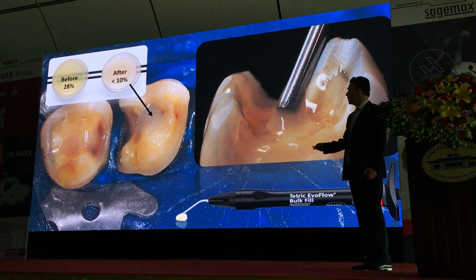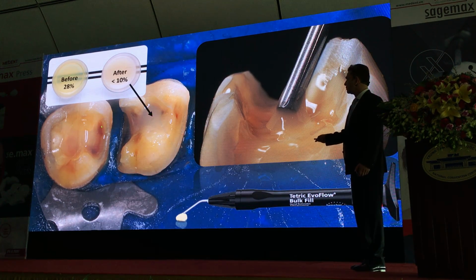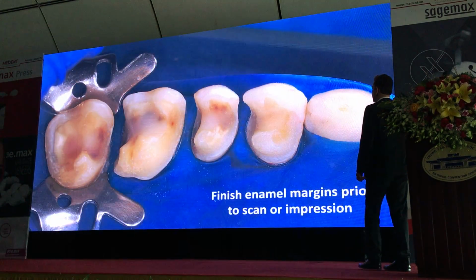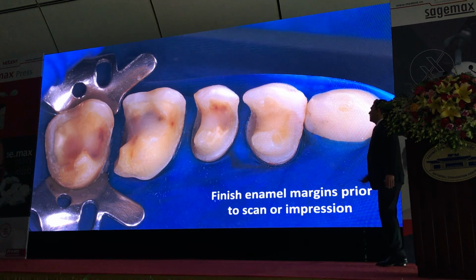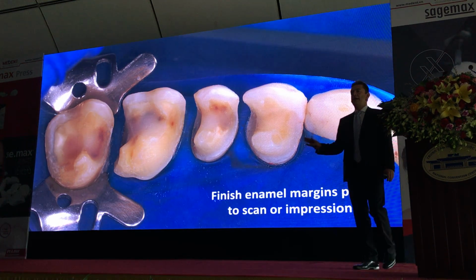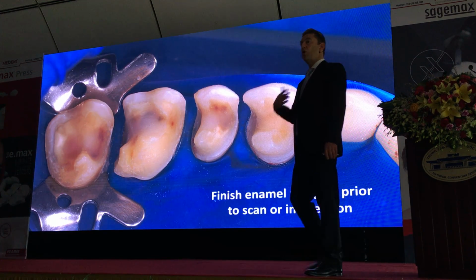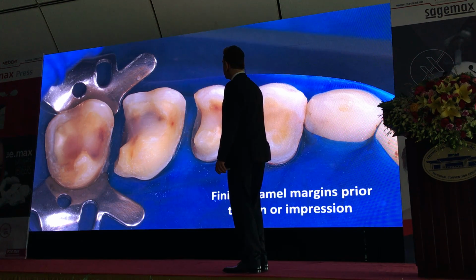So you can see you can block out. If you have some areas which are more dark, you can block it out with this flow. Okay, so this is the situation. I finished my enamel margin after immediate dentin sealing and blocking out the undercuts. I have a very, very clean situation now, okay? Now this is a perfect condition.